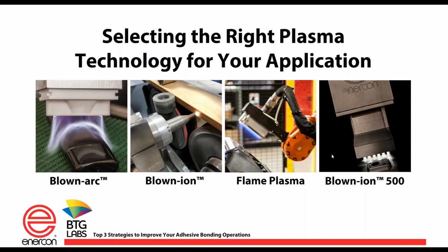With the 500 on the end, it is a blown ion. From the second picture, it's kind of its grown-up big brother. It is a multi-port design. You can see it's got 6 ports there. Generally, this will treat 50 millimeters, thus the name 500, or about 2 inches. And the advantage that this has is many of our competitors have 2-inch heads, but what they're doing is taking one blown ion head and using a special nozzle and spinning it around to create that 2 inches of area.